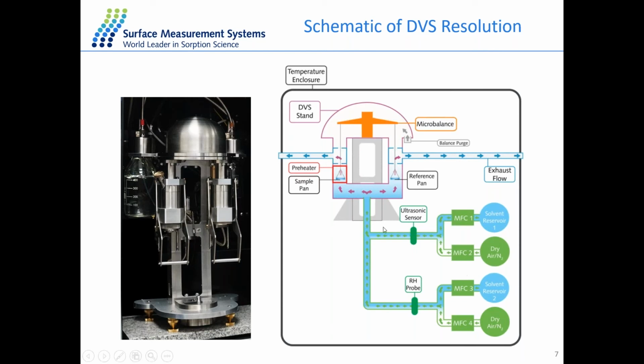So this mixture will flow to both the sample chamber and the reference chamber at a constant rate, and the sample inside this chamber will pick up the moisture. Then the mass will be recorded by the balance. The whole setup will be set in an incubator with a temperature range from 5 to 85 degrees, which means we can perform experiments over a very wide temperature range.